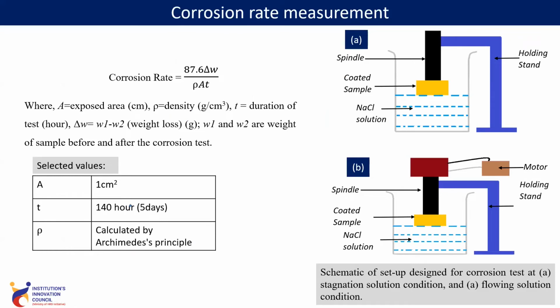Corrosion rate measurement is performed. This is the corrosion rate formula that we have used to perform the corrosion resistance analysis. This is the setup that we are using: a spindle attached to the coated sample, then NaCl solution, a 1 centimeter square area, and we are performing it for 140 hours, and density is calculated by Archimedes principle. So the stand that we are using is a spindle. First of all, we conducted the corrosion resistance analysis under stagnant solution condition, and then we used a motor, with the analysis performed under flowing water condition.